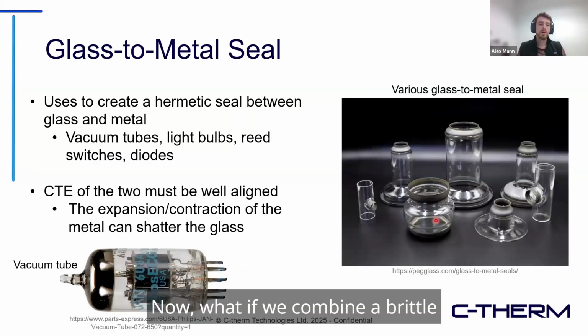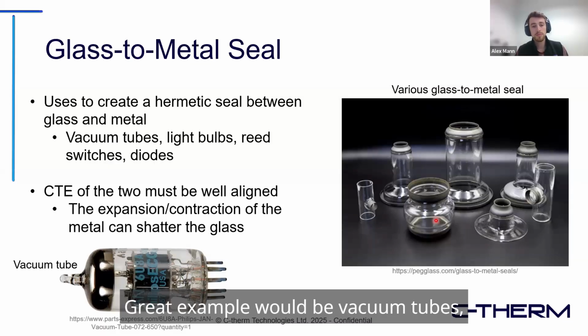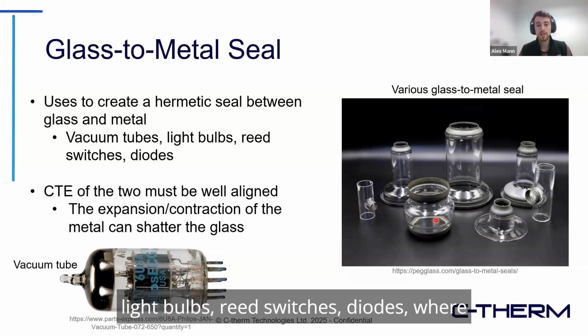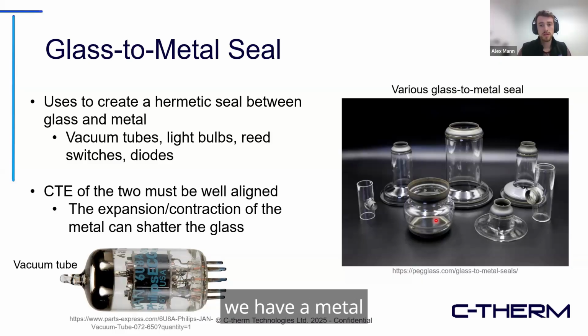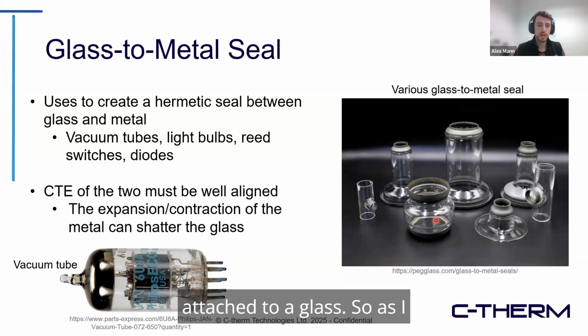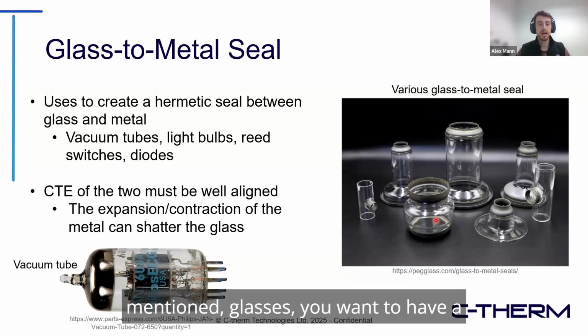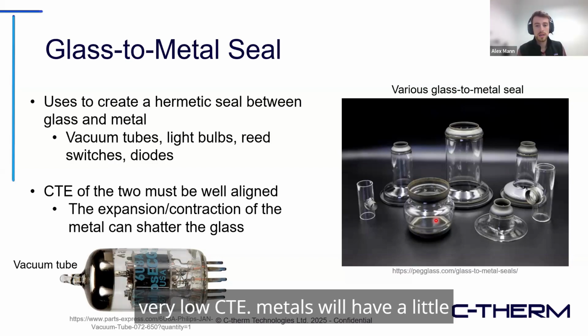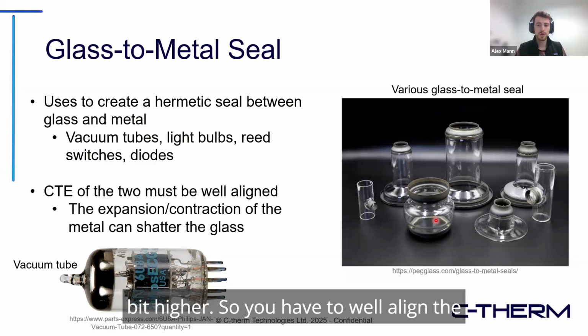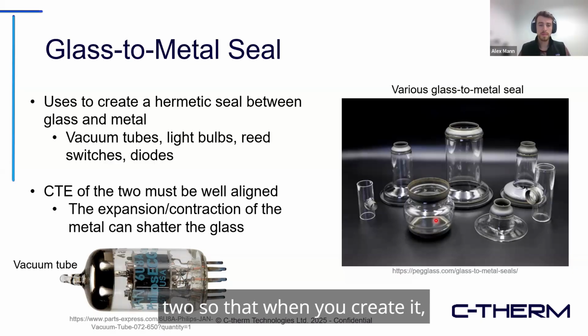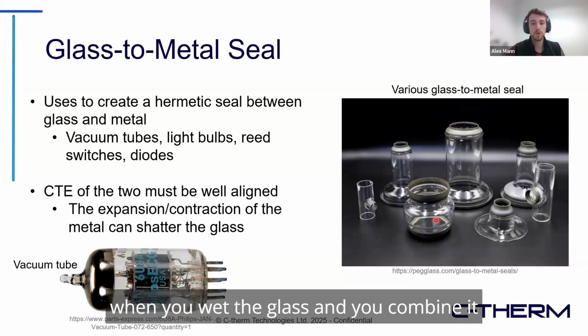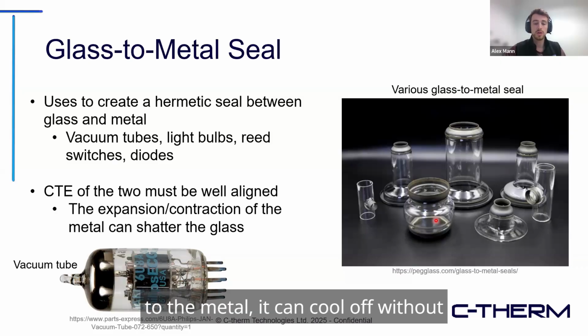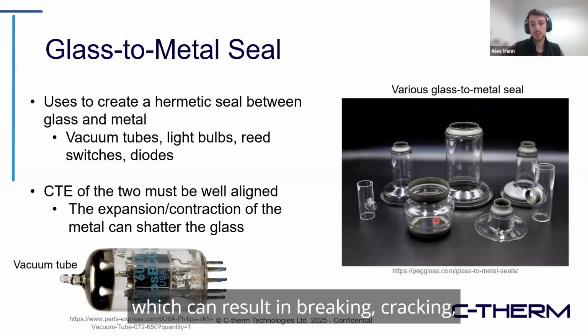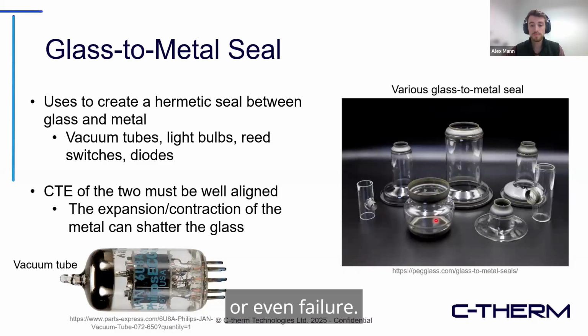Now, what if we combine a brittle material and a ductile material? A great example would be vacuum tubes, light bulbs, reed switches, diodes, where we have a metal attached to a glass. So as I mentioned, glasses, you want to have a very low CTE. Metals will have a little bit higher. So you have to align the two well so that when you wet the glass and combine it to the metal, it can cool off without causing a large stress on the glass, which can result in breaking, cracking, or even failure.